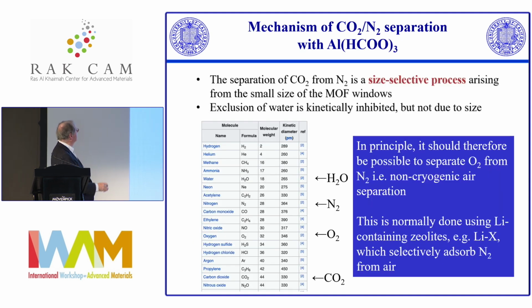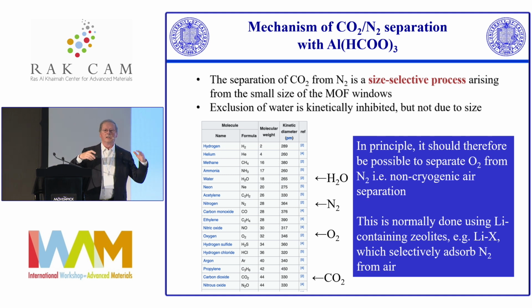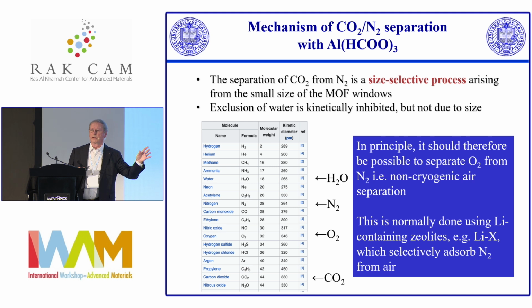And we were looking at these kinetic diameters on the basis that this is a size-selective adsorption process into the ALF. And we know that nitrogen won't go in, so one of the first things we thought about was maybe oxygen will go in, because oxygen's significantly smaller than nitrogen. When I say significantly smaller, it's probably 2/10 of an angstrom or something like that. It's kind of minute, but it nevertheless is smaller.